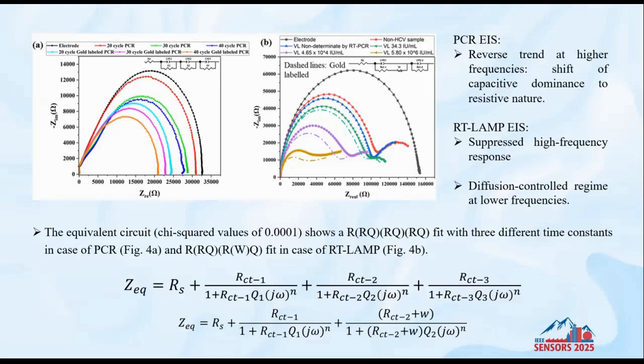This can be due to reducing surface charge transfer processes owing to a shift of capacitive dominance over the impedance measurements to resistive nature. However, in the case of RT-LAMP, the dense layer of long-looped hybridized DNA severely hinders the charge transfer right from the start, thereby suppressing the high-frequency response. The impedance behavior shifts to a diffusion control regime at lower frequencies, giving rise to a Warburg component. The RT-LAMP EIS plots presented through Nyquist plots show a progressive reduction in impedance with increasing viral loads.